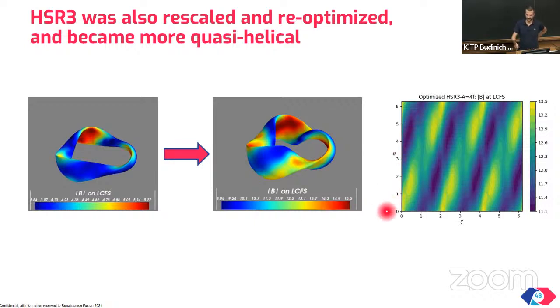For completeness, these other contours on the right, this is the field strength, again on the last closed surface. Basically, if you take the torus and you unwrap it, and you plot the field strength as a function of the poloidal and toroidal coordinate, you get these nice stripes. So this is a quasi-isodynamic stellarator, which basically means your particles, even where they are trapped between maxima of magnetic field, are not drifting away from the plasma. They stay close to it. And at the same time it is quasi-helically symmetric, with the field patterns as a function of the toroidal and poloidal coordinates. Both are properties that yield good confinement. When it looks like stripes, it's a good sign.